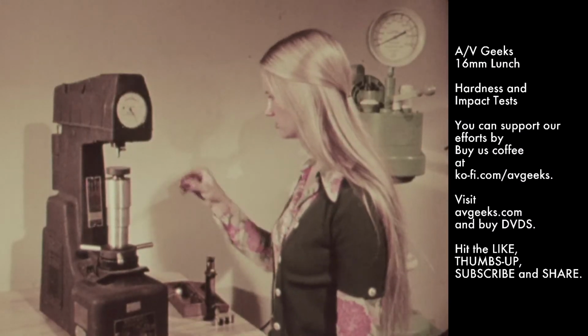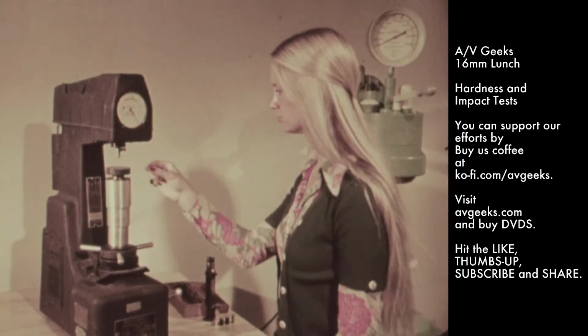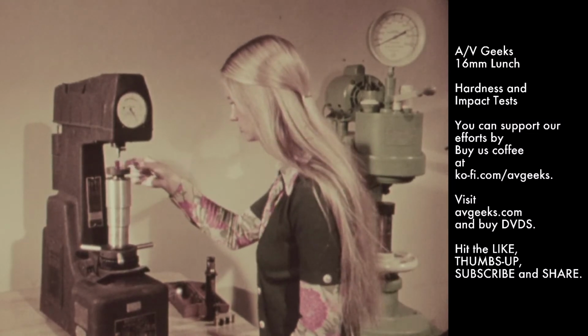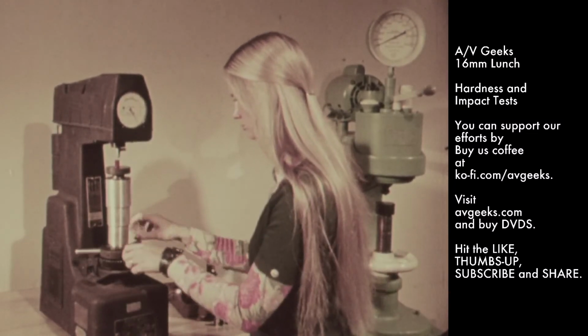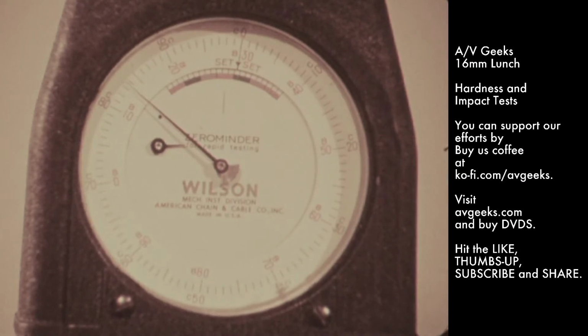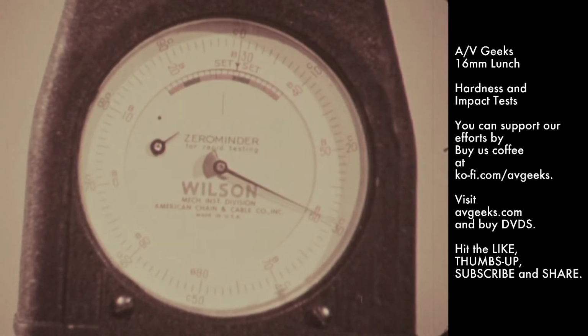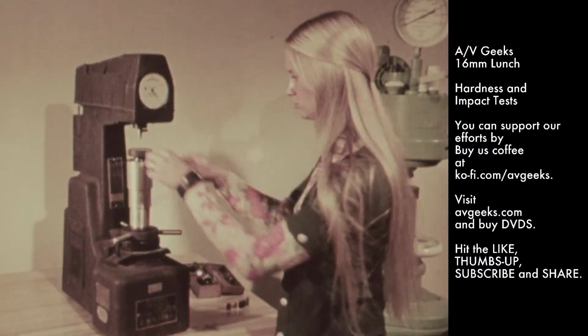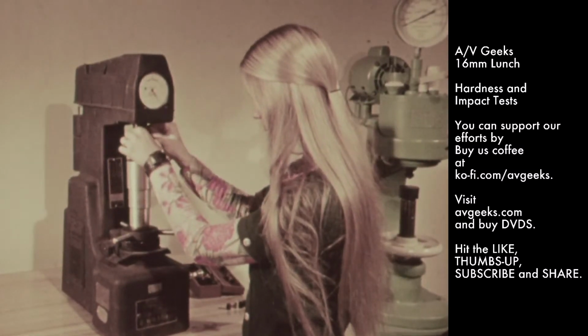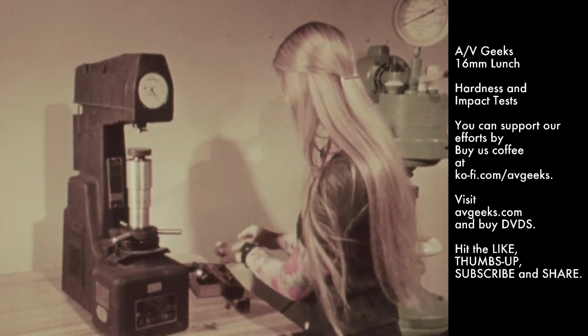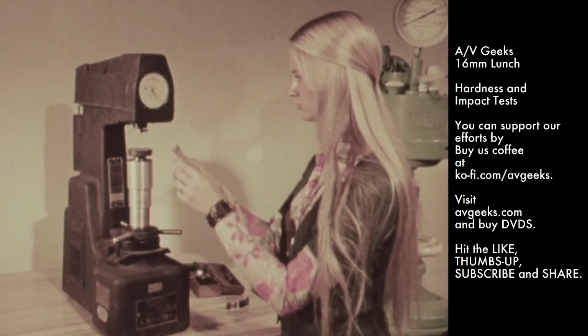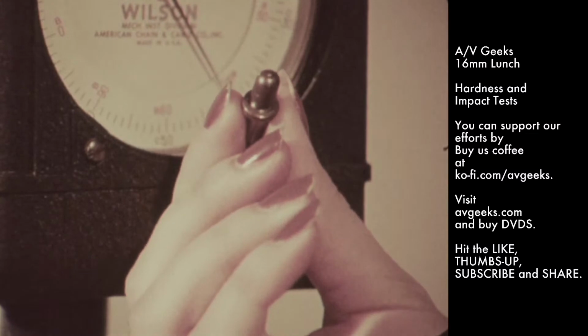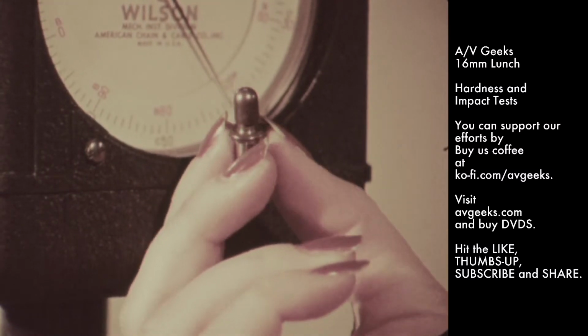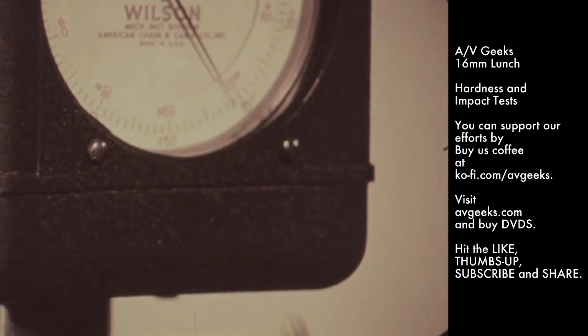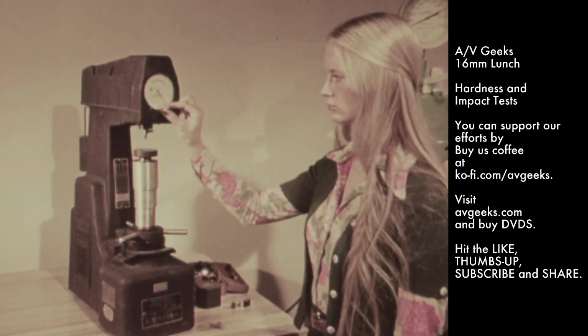A similar test is performed on ASTM 1095 steel, which contains 0.95% carbon. Here, the hardness number is C30. For a softer material, the diamond cone would penetrate beyond the reading capability of the instrument. Hence, the 1/16 inch diameter ball-tipped penetrator is used analogously with a 100 kilogram load.